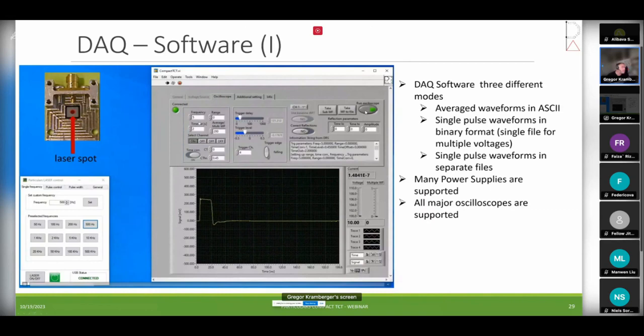We'll come to that later. So this is how the pulse looks like at 10 volts. We set it to 10 volts. This is again the same sample that was shown in the previous analysis. So this is the P on N sample, high resistivity. You see, we inject in low field at 10 volts. It's not depleted, and therefore you have this long tail. I deliberately stretched it so that you can see how long the tail looks like.